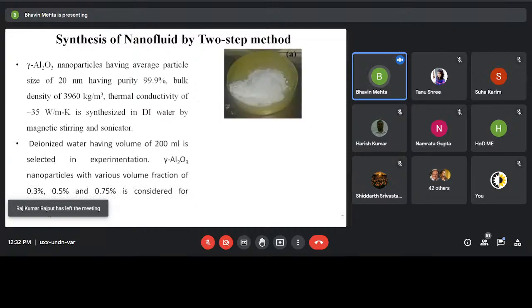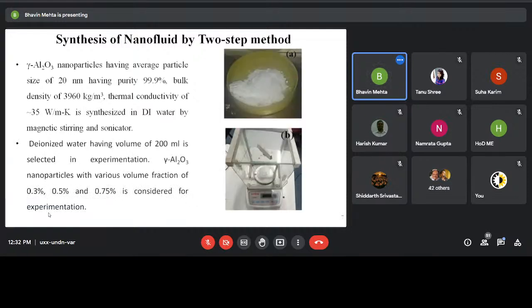Now, in this experiment, we have taken Al2O3 nanoparticles with a 20 nanometer particle size. The density is 3960 kilograms per cubic meter, and the thermal conductivity of the particles was observed as 35 watts per meter Kelvin. We purchased it from NanoShell. Deionized water of quantity 200 ml is considered for the experimentation, and the nanoparticles were added to this base fluid at various volume fractions: 0.3%, 0.5%, and 0.75%.